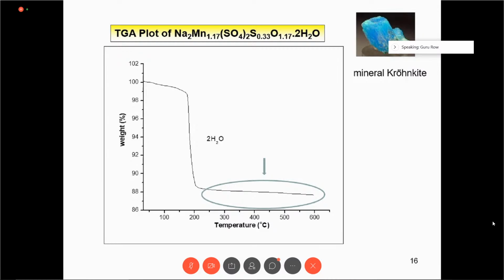So we take this compound and subject it to DTA studies. DTA is differential thermal analysis, and thermogravimetry, it is actually TG, which is shown here. The thermogravimetric analysis essentially sees how the compound decomposes as we heat it. So when we reach a temperature of about 180 to 190 degrees, you see this particular compound undergoes a change. It loses 2 water molecules, and then it goes to a phase which is very stable.